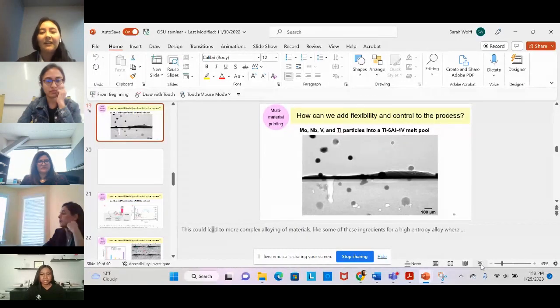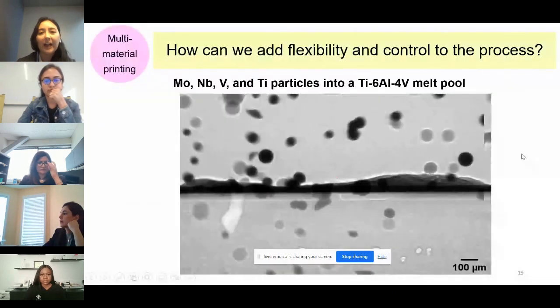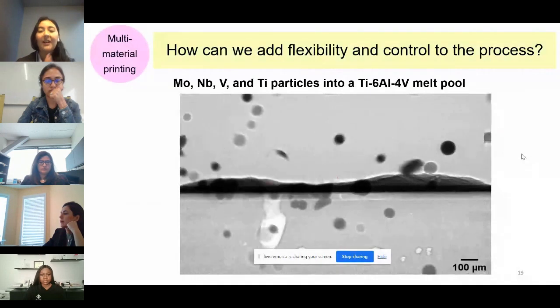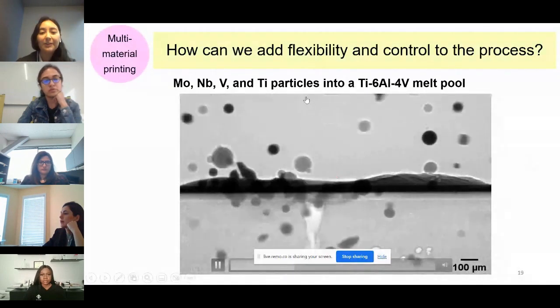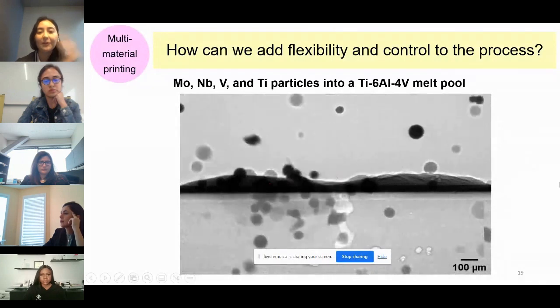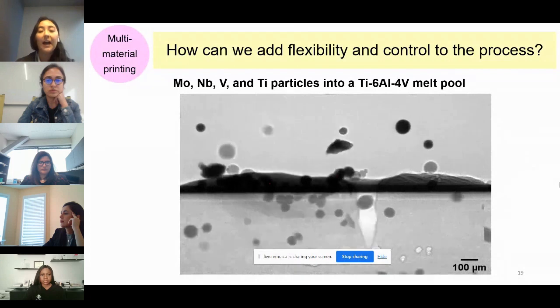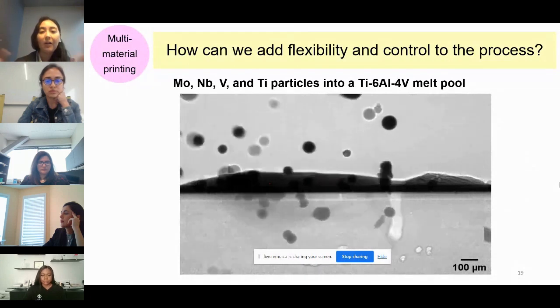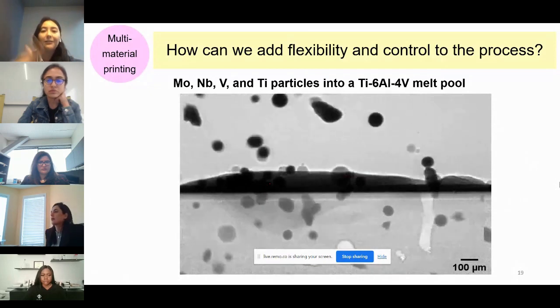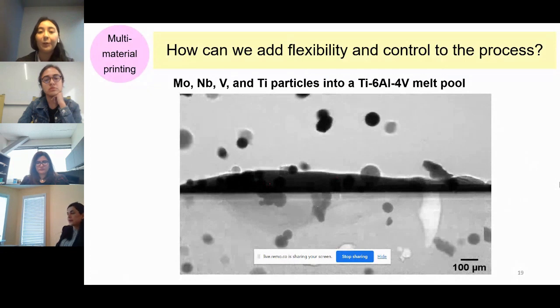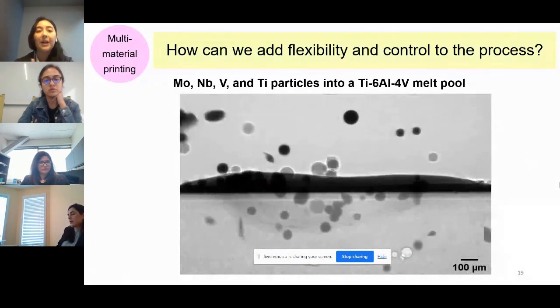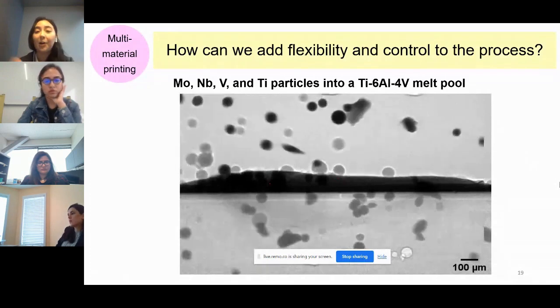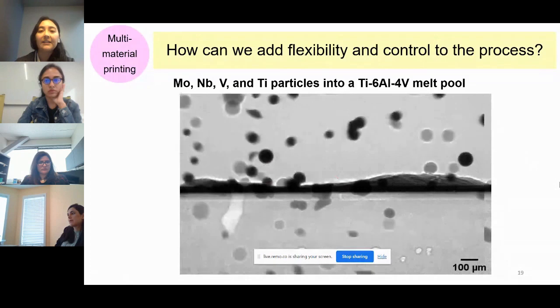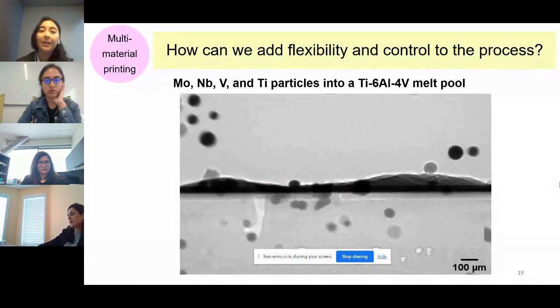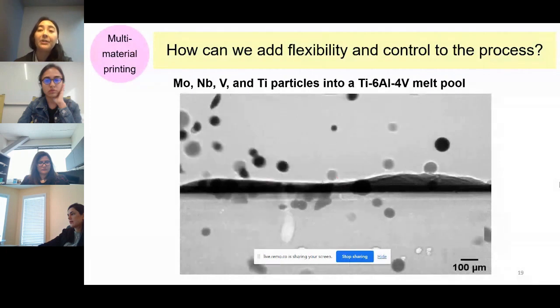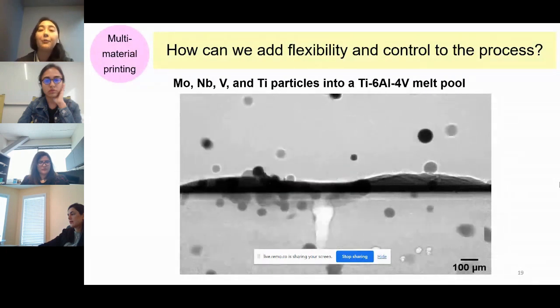Like I said, in a lot of my work, I use real-time imaging, so process monitoring during the process. There's a lot going on here, but what's happening is we're using a laser moving from left to right to melt metallic particles. And as I mentioned in the first question, we're depositing different elements into a melt pool, a liquid pool of metal. We're depositing molybdenum, niobium, vanadium, titanium. The reason why we want molybdenum and niobium is that's your refractory, high density, high Z, really harsh environment type of elements. But vanadium and titanium are also high strength, and they provide a lot of that lightweight material.